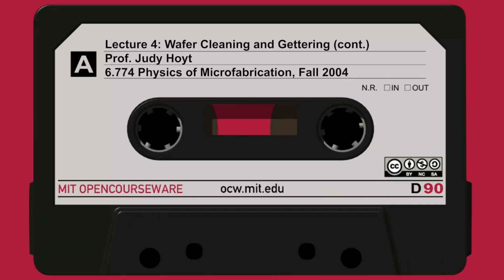And it has some exponential dependence on an activation energy, EA1 over KT. And the second equation down is the solubility of gold in the gettered site, G. So it's got this G next to it in the gettered region. And here, N sub G is the density of gettering sites. N sub silicon here is the density of silicon atomic sites.